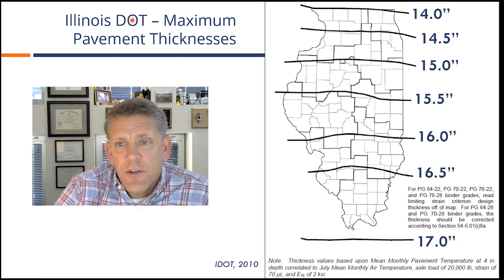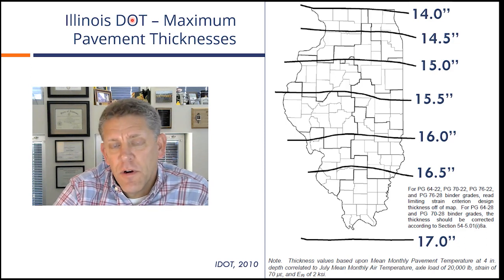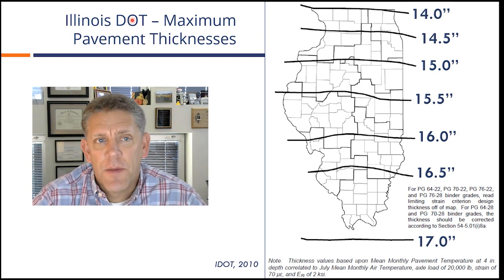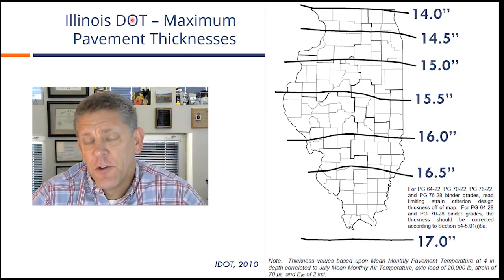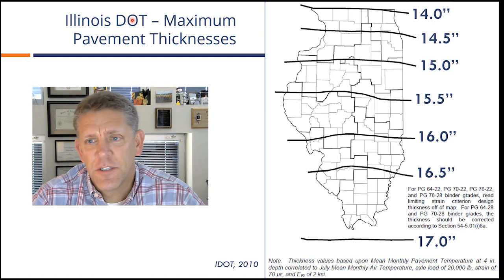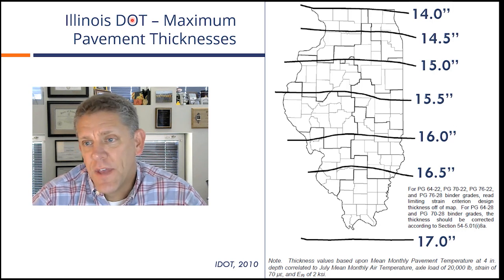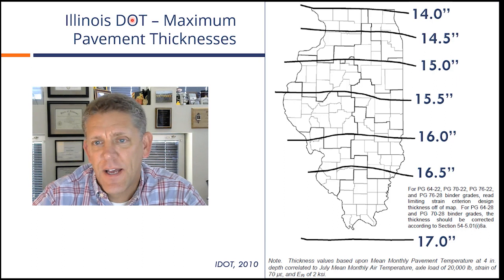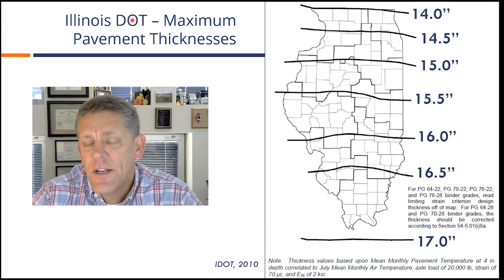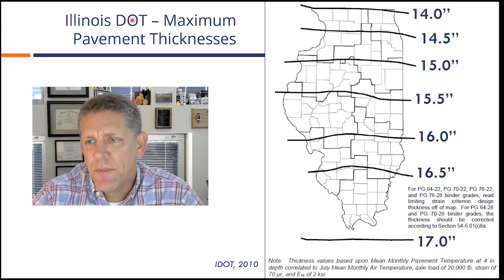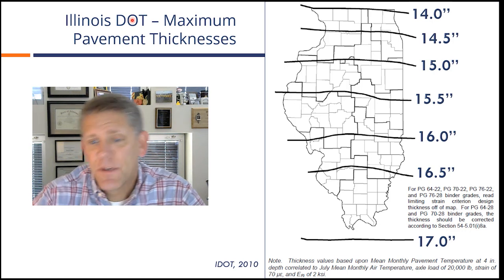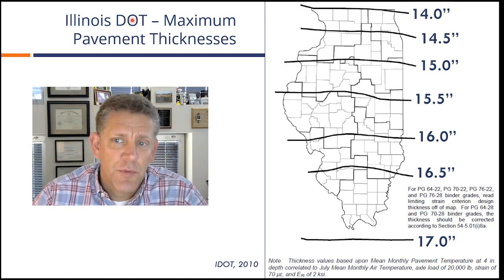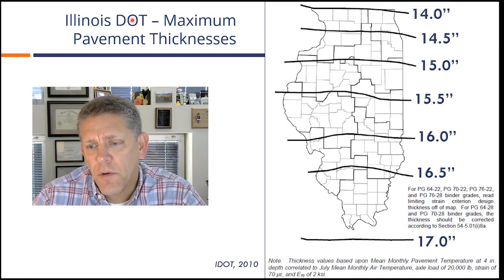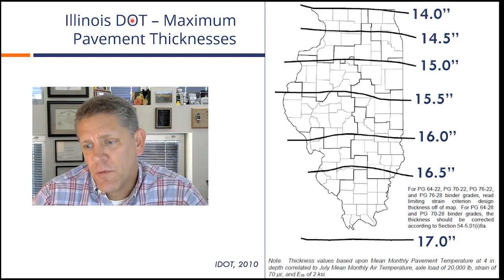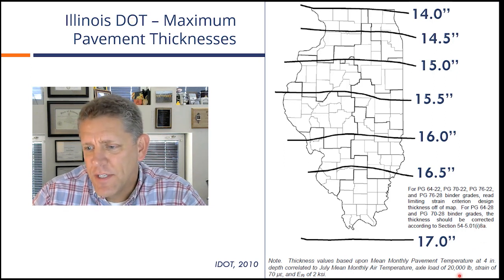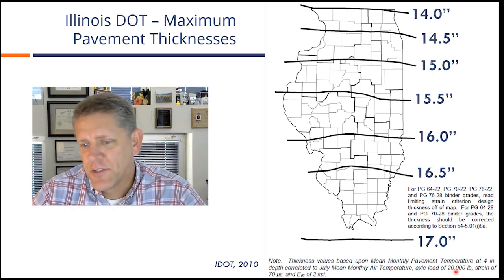I should also point out that using strain distributions and PerRoad or PaveExpress aren't the only way to go about coming up with maximum pavement thickness. The Illinois DOT has had for a long time in their design code an approach that essentially you do a conventional pavement design and then you check it against a map like this to look at what is the recommended maximum pavement thickness, and if you exceed that, then it's capped. And their approach is quite a bit simpler and more straightforward than using PerRoad or PaveExpress. They look at the hottest month, the heaviest design load here. They use an axle load of 20,000 pounds.